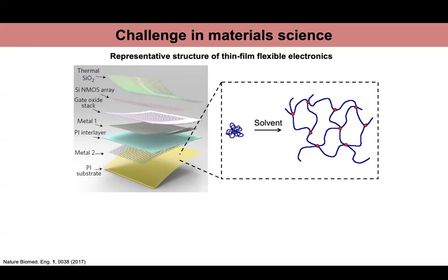The first one is that when a material is soft, what enables the softness, that is the glass transition temperature, is lower than room temperature. You can consider them as cross-linked liquid at room temperature. Or they actually have this micron porous structure so that they can enable the stretchability.